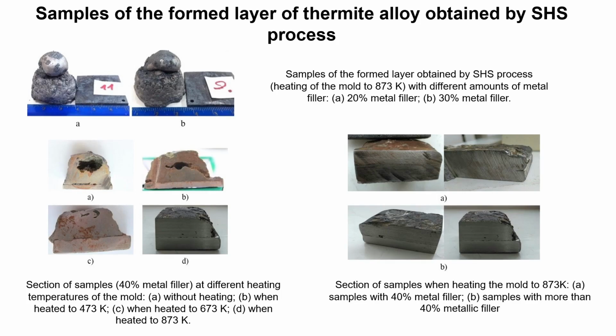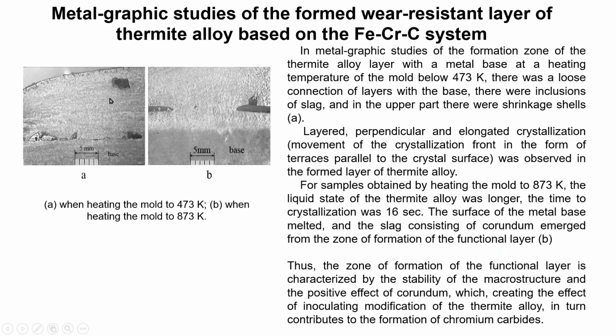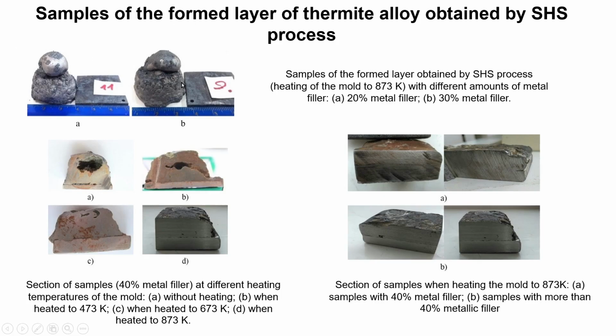Thus, as a result of the process technology, samples of thermite alloy are obtained on the surface of which, when the mold is heated to 873 kelvins, in the slag phase metal inclusions of spherical shape are formed. This is due to the rapid stage of combustion and is accompanied by intense spraying of the resulting synthesized metal. In the study, 40% of metal filler was added to the thermite charge.